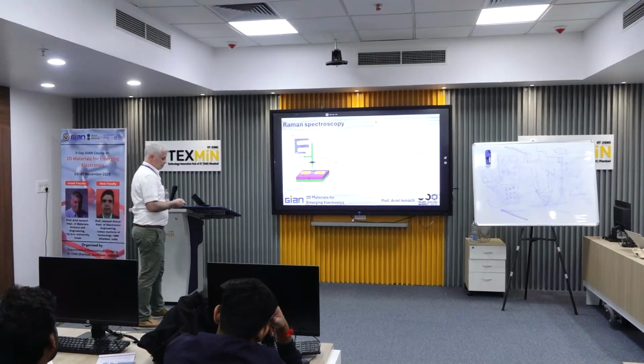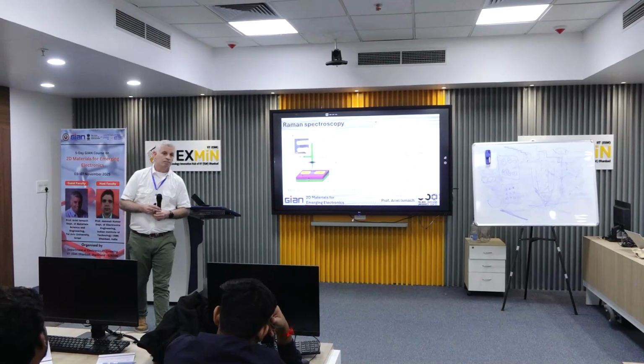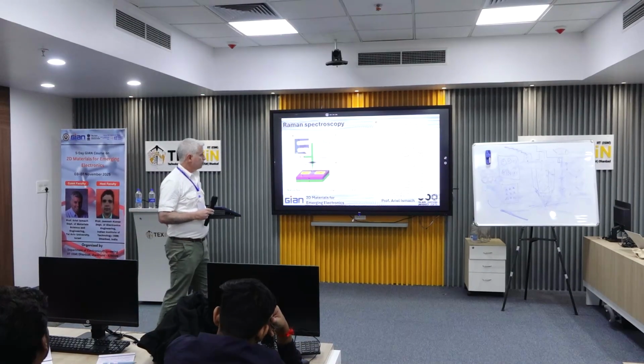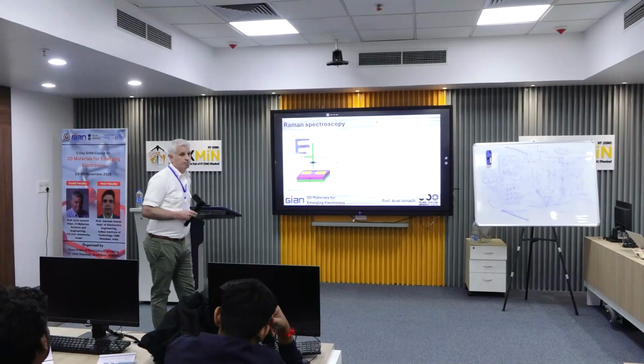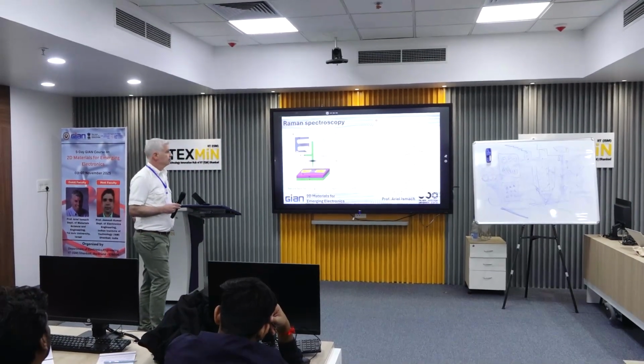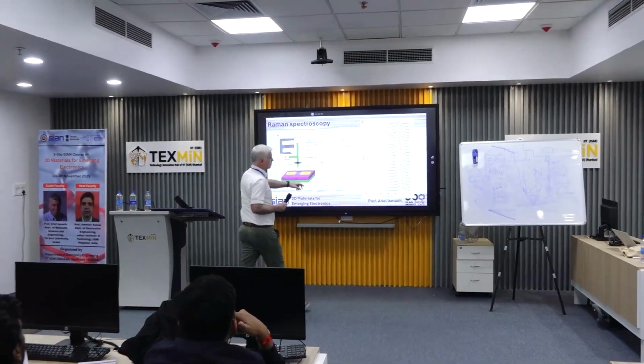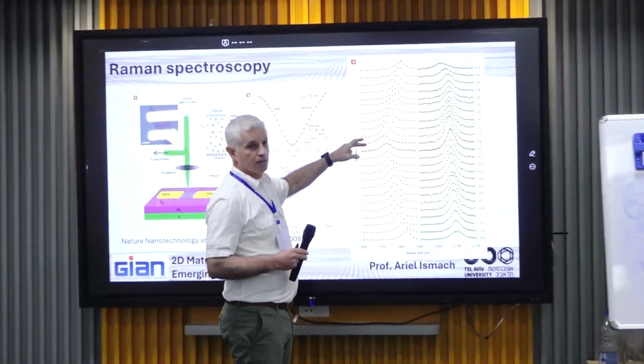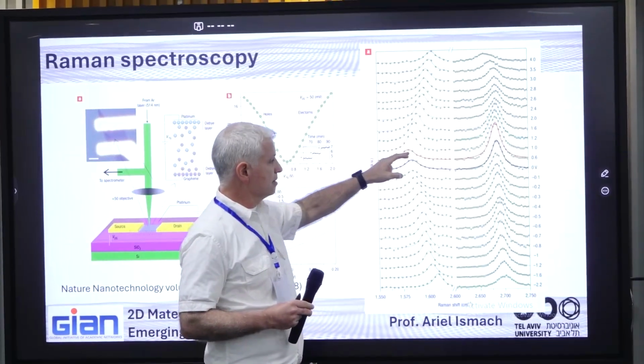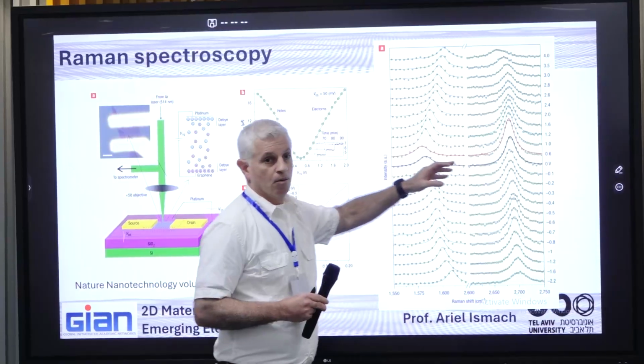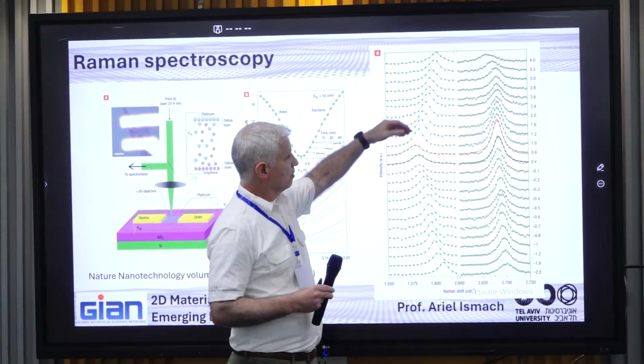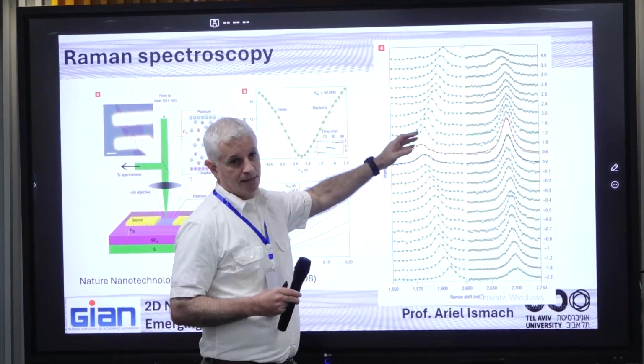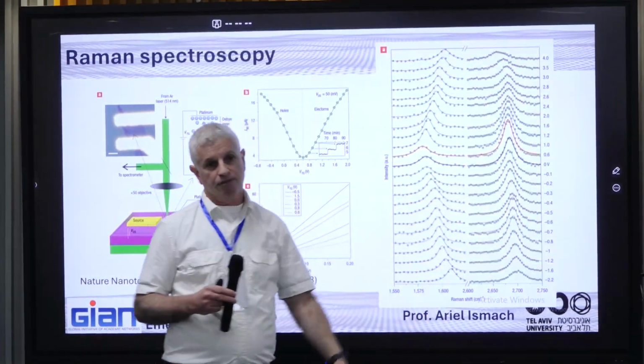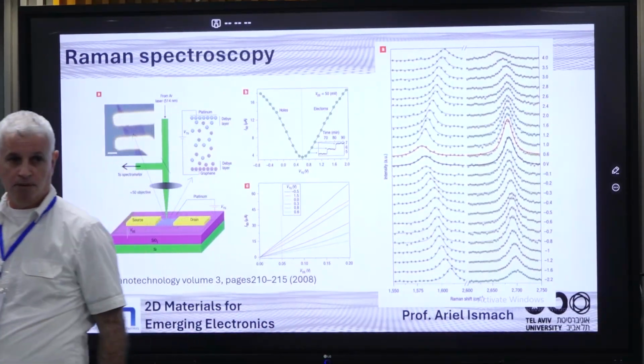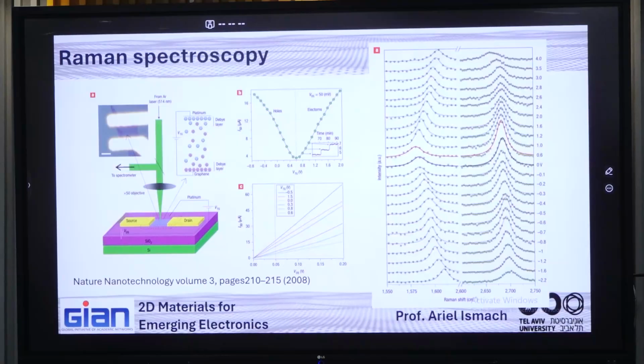Sir, one thing. The curve shifted to the left side, and then again it shifted to the right side, right? What does it indicate after a certain voltage? No. We start from this point. This is the zero. Once you charge it, it doesn't matter if holes or electrons, you get the same or a similar shift of the G mode. So the G mode is not selective to holes and electrons.